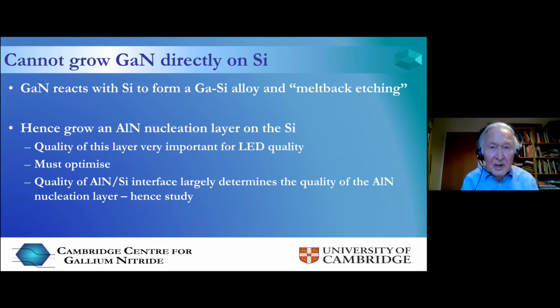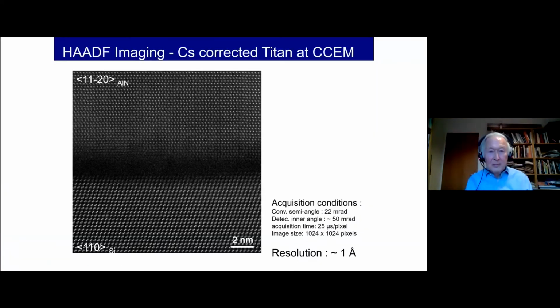And what we found when we did atomic resolution electron microscopy, so here, this is aluminium nitride at the top, silicon at the bottom. We're growing the aluminium nitride on the silicon. This is a cross-sectional electron micrograph. The double dots you can see in the silicon, each dot is a column of silicon atoms. And so this is really high resolution microscopy. We're seeing the individual atoms in the material. And that's a 2 nanometer scale mark at the bottom.